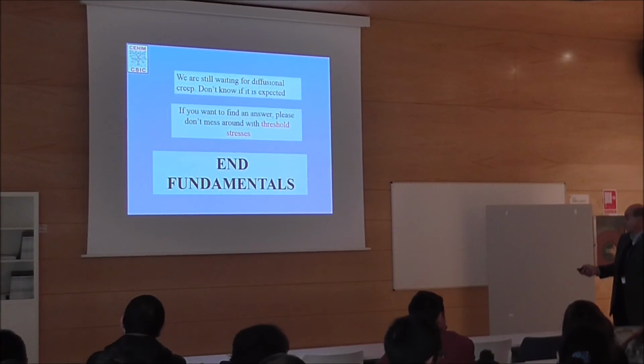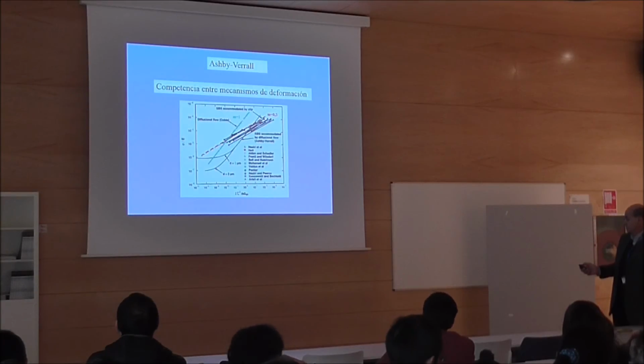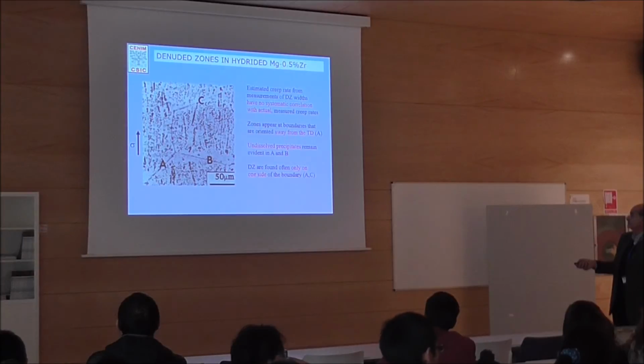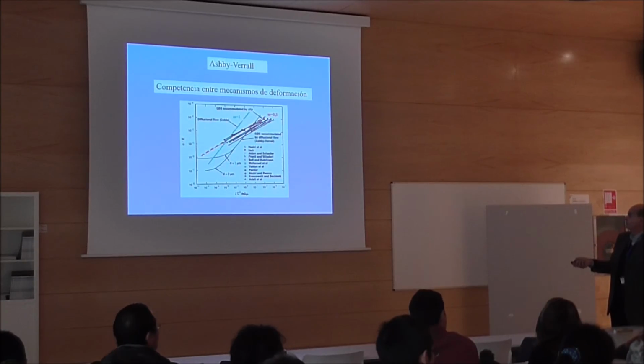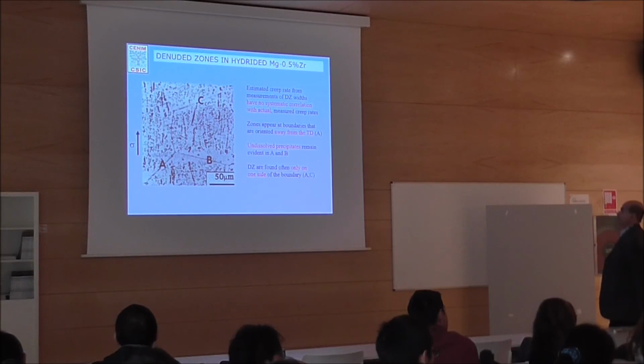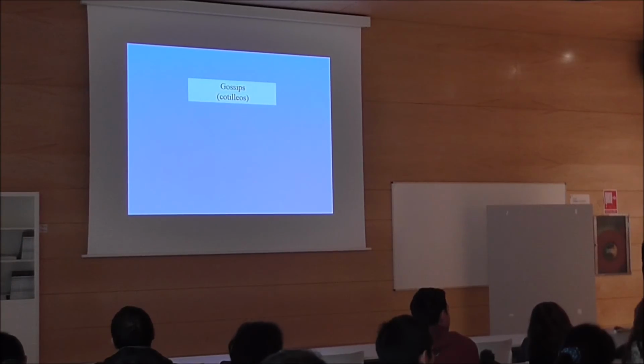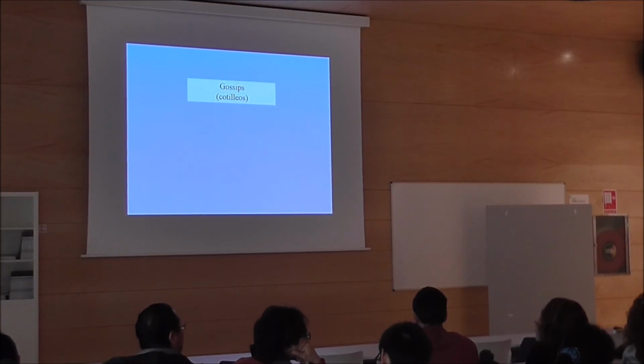Although if you put all the stresses in line, you will see that yes, it is changing. But you see that this is good for n because of the stress components. Maybe you can compare pairs. So if you are in one microstructure steady state and it changes to another strain rate, for these two you can really compare, because you're sure that you have the same microstructure. Yes. And then you can do it two by two. If you do it in pairs, then you are sure that you have the same microstructure. With a lot of strain jumps, maybe jumps very far away, you cannot compare with the previous, but by two, in pairs, I think they are comparable.